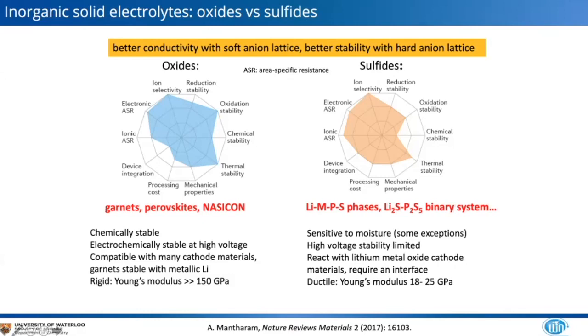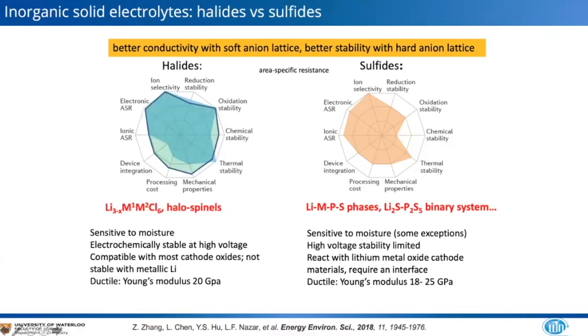And then a new player on the block are halides. And so the halides are also somewhat sensitive to moisture. They are encompassed by materials such as Li3MCl6, where M tends to be a rare earth, and also halospinels, which I'll mention at the end of my talk. They actually are compatible with most cathode oxides, although they're not stable with metallic lithium, but they enable cathode oxide materials to be used without a protective coating. And they also have the advantage of good ductility.